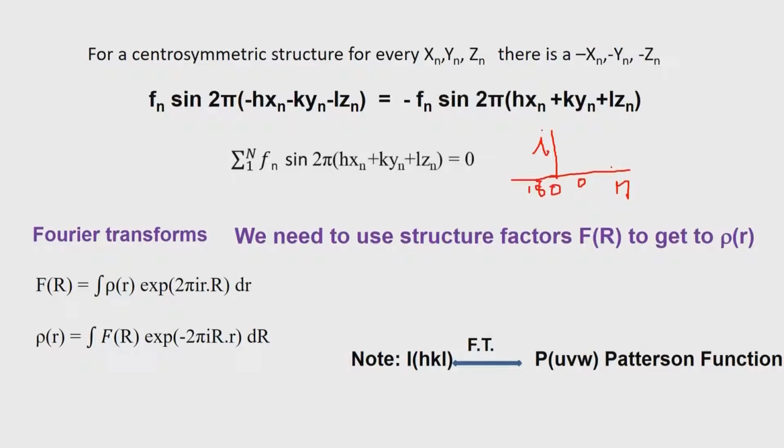So, the phase factor associated with centrosymmetric structures can be only real quantities, and therefore, in other words, we use only the cosine function in order to calculate the intensity. We will examine later on the reason why this becomes very crucial and of extreme importance to solving crystal structures. But at this particular moment, we should remember that in centrosymmetric structures, the phases are either 0 or 180 degrees associated with every HKL reflection. On the other hand, in the case of non-centrosymmetric structures, it can be anywhere in this 0 to 360.